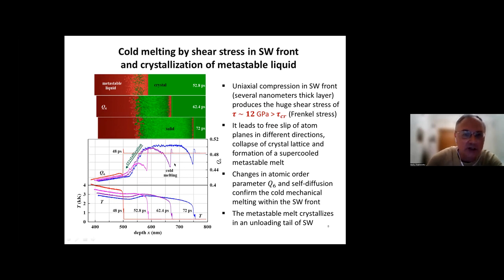Later I will show that, of course, it's not enough to show just configuration, position, or disorder in position to distinguish between amorphization and real melting. We have to apply additional analysis of kinetic coefficients like viscosity and self-diffusion in order to confirm that we observe a real melting.